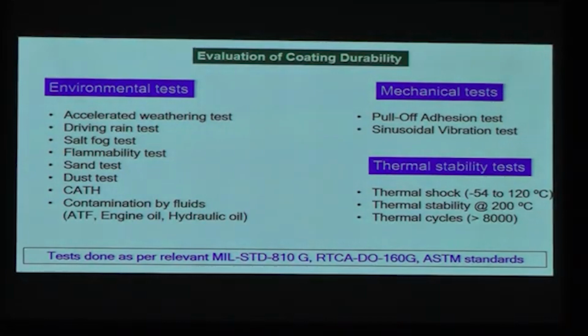The coatings have undergone rigorous testing. As we can see over here, they are listed here. They have been tested for their environmental durability, like accelerated weathering test as per ASTM G154 for 500 hours. And after the test, the coatings have been tested for their adhesion onto the substrate as well as for their thermal insulation behavior. The coatings were tested for their intactness using C-scan technique. Followed by this, the coatings were tested for driving rain, salt fog, flammability, sand, dust, and contamination by 3 different kinds of fluids which are commonly encountered on aircraft. All these tests were carried out as per relevant military standards, RTCA and ASTM standards.